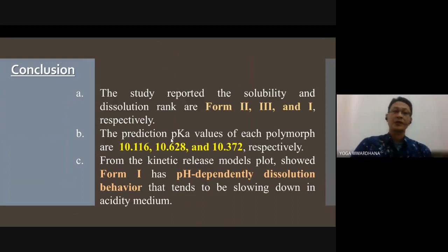10.372. And for the kinetic profile, we found that form 1 has pH-dependent dissolution behavior that tends to be slowing down in acidic medium, changing from the Higuchi model in the acidic medium to the first order profile. Thank you. That's all my report.